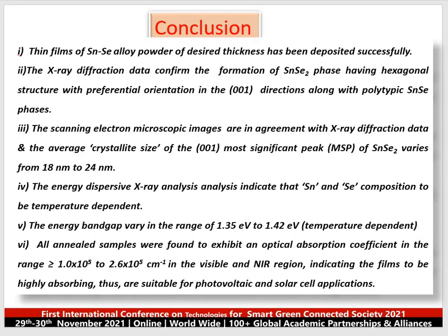All the annealed samples were found to exhibit an optical absorption coefficient in the range 1 × 10^5 to 2.6 × 10^5 per centimeter in the visible and NIR region, indicating the films to be highly absorbing, thus suitable for photovoltaic and solar cell applications.